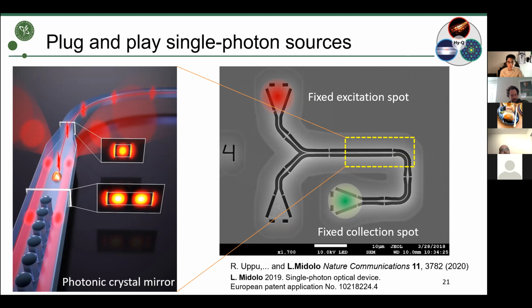So there are some practical challenges there. As I mentioned before, there is this concept of self-assembly. The quantum dots are nucleating at random positions, at random wavelengths. So controlling and finding dots that are exactly identical to each other is very hard. This is why we need local gates and controls, and this is a lot of work also on the fabrication side, but we are working on this. We are writing something right now about making 2 of these on the same chip, and potentially this can go further.